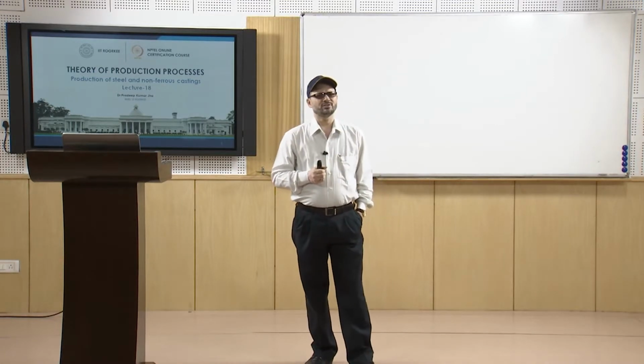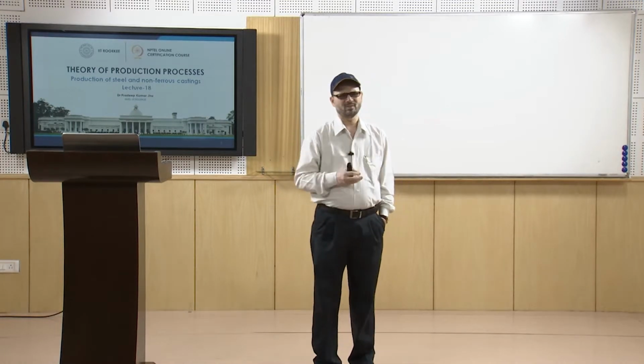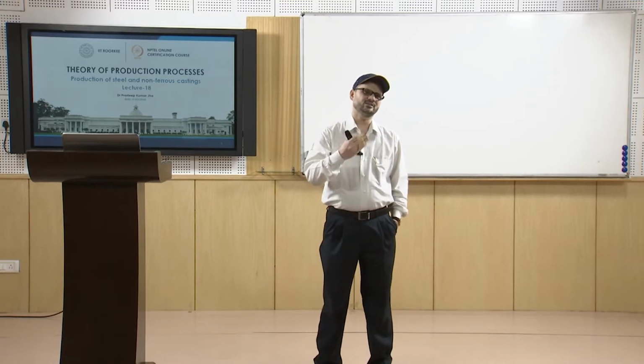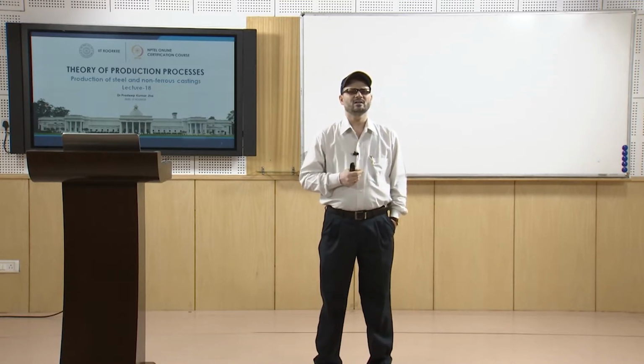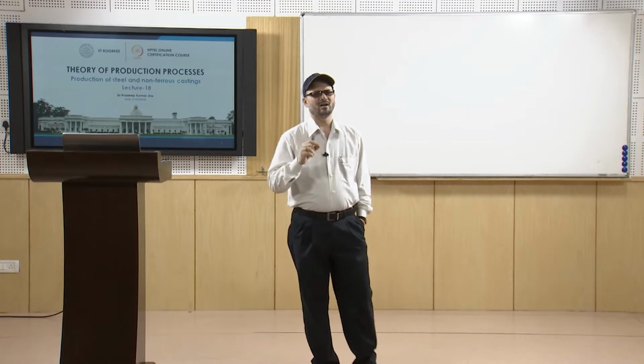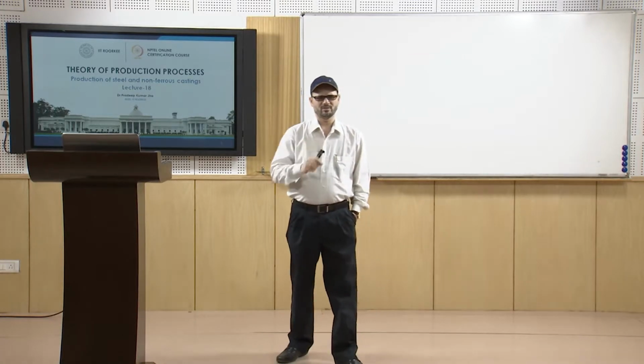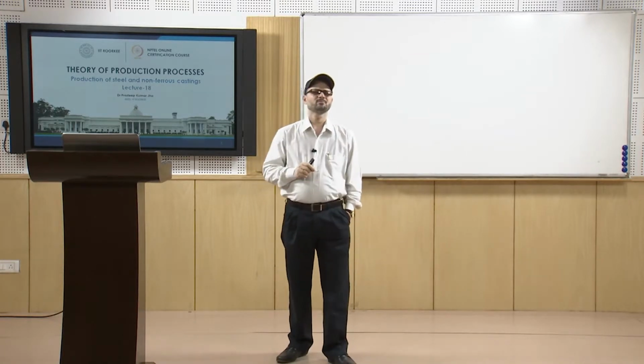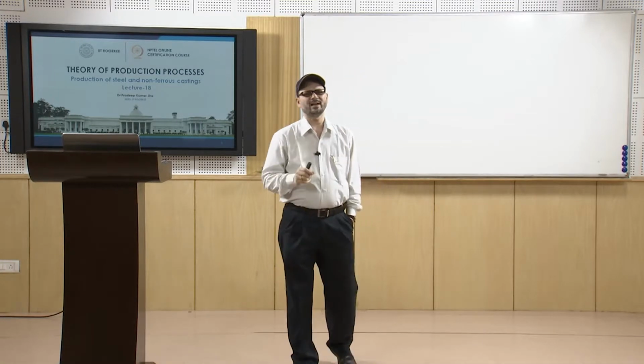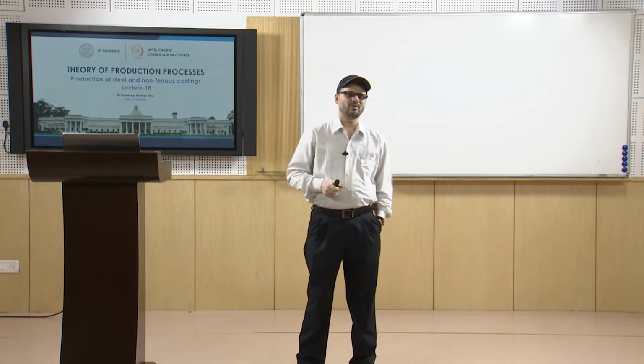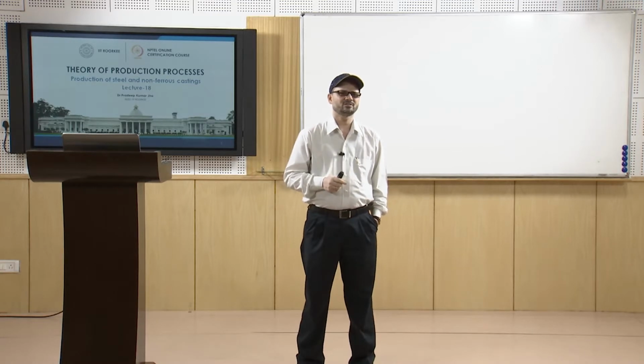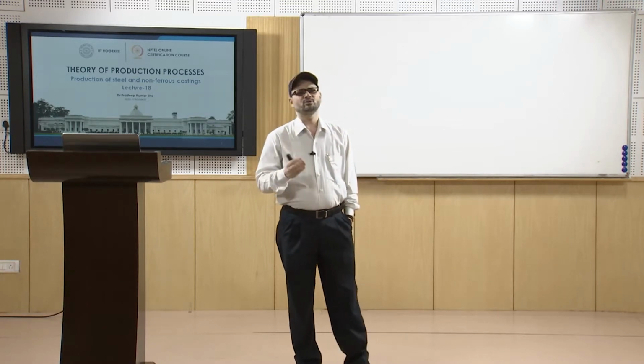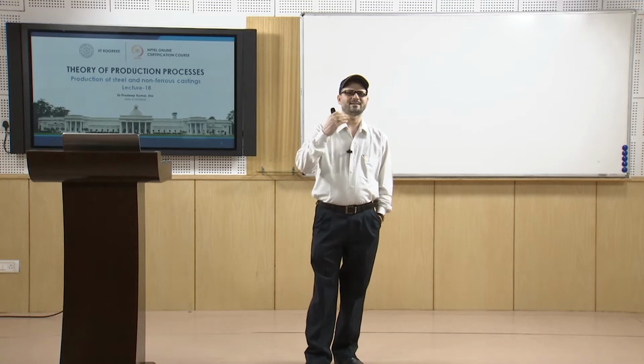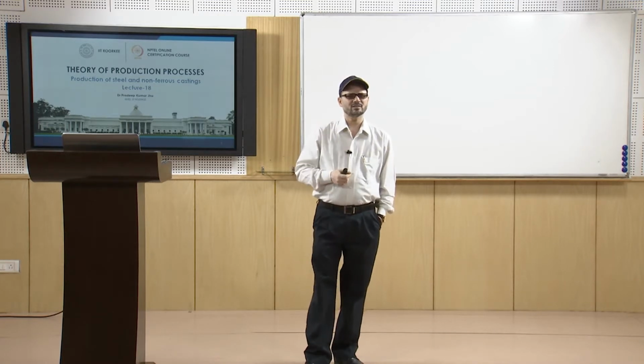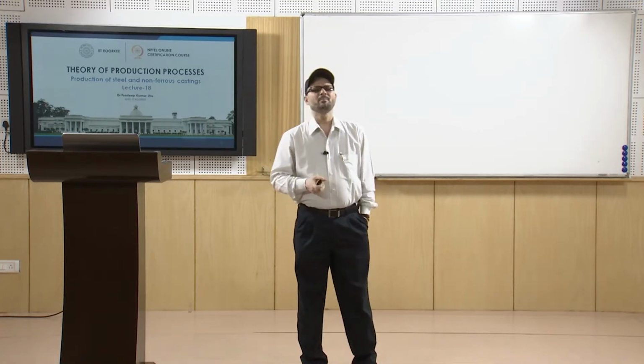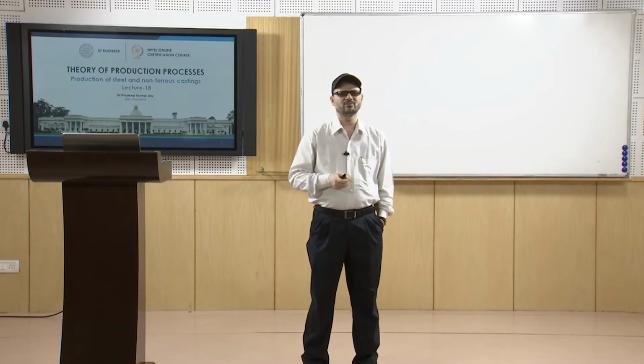No carbonaceous materials or washes should be there, because as we know, this is a challenge in steel casting, that there should not be carbon pickup. So, that is why we have to be careful about it. Use of new facing sand, because that will provide better refractoriness, and the tendency of fusion at the surfaces will be lesser. So, that should be there. Metal must be deoxidized before pouring.